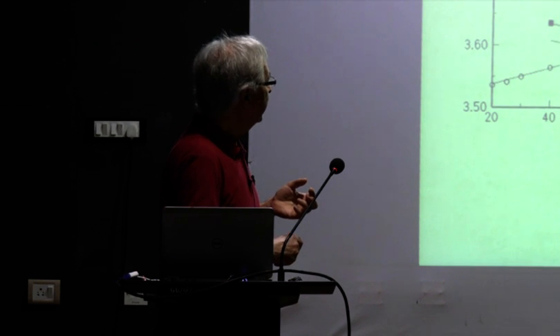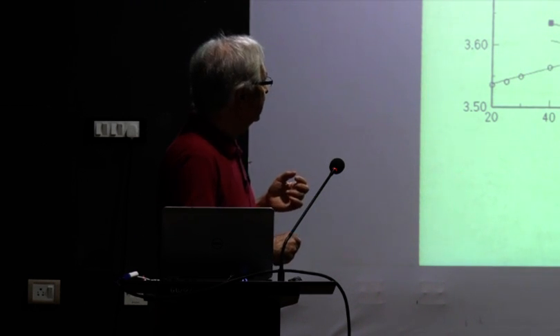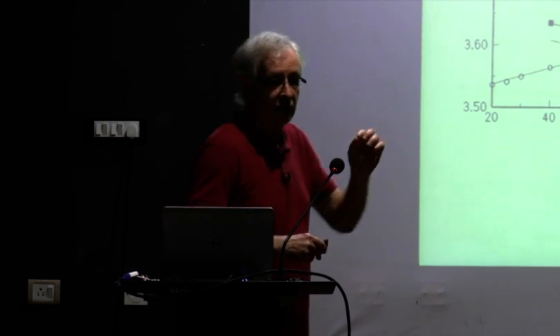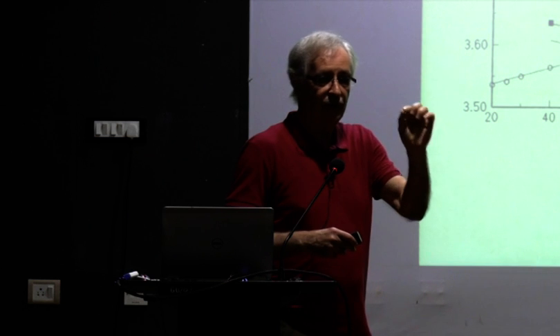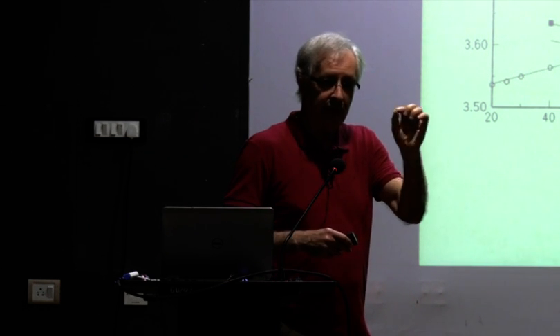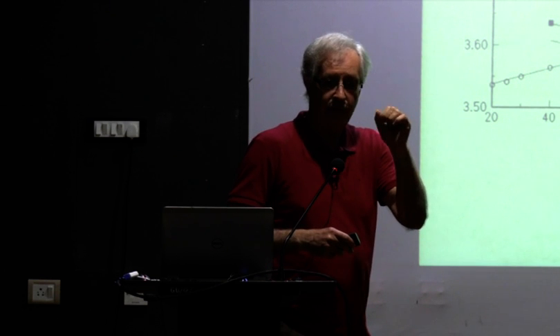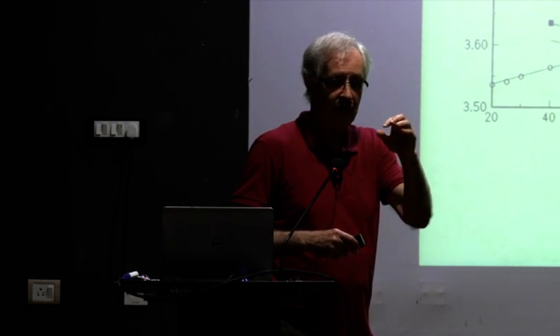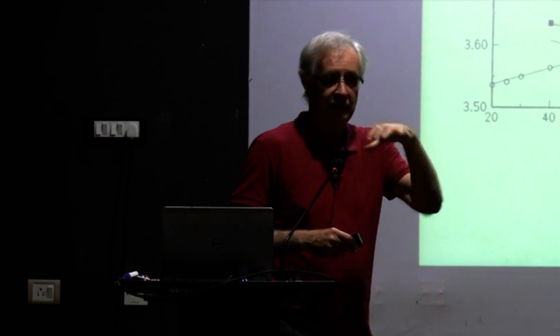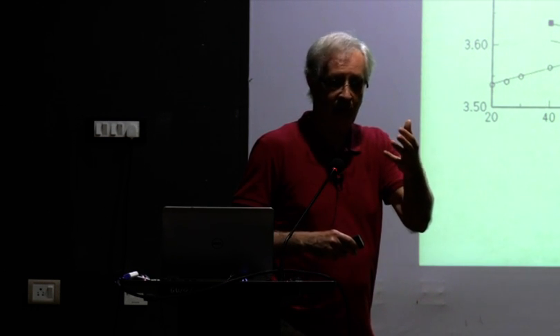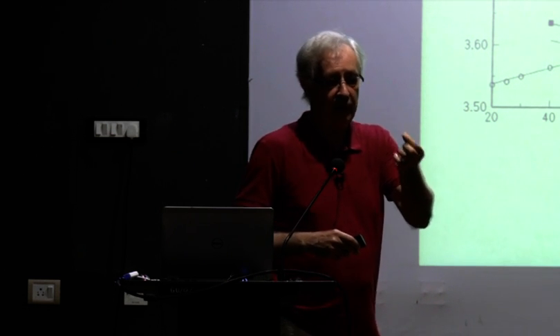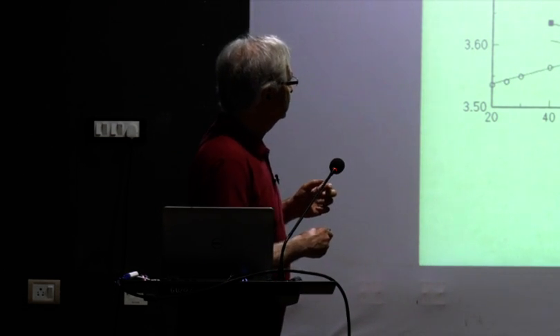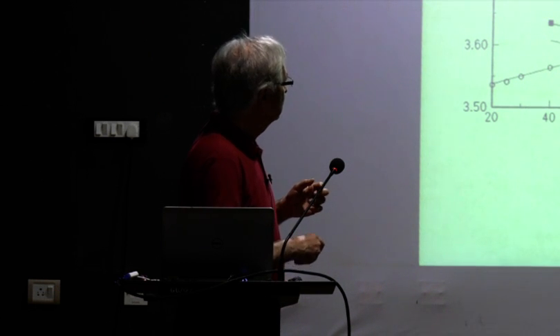This is the estimated hyperfine field in iron, in gamma iron. And here, you can also make an alloy with a very small concentration of iron in copper so that you have coherent precipitates. Coherent precipitates meaning that iron is in the FCC state as with copper. But this happens only when your particles are very, very small. And when you do experiments on that, you get results which are similar to that.